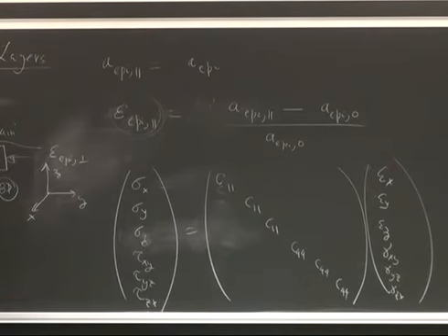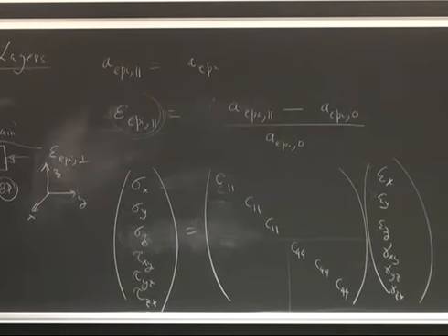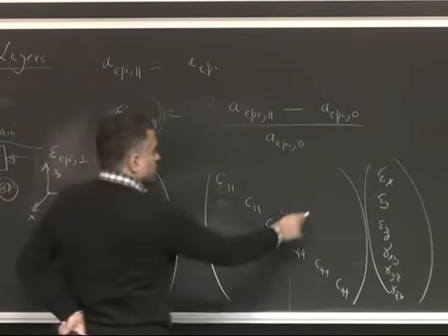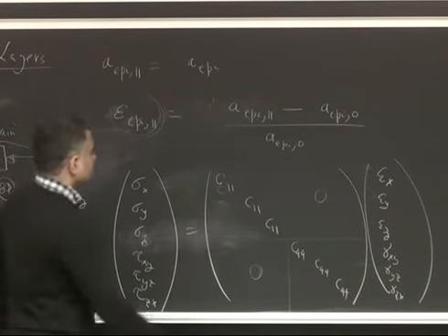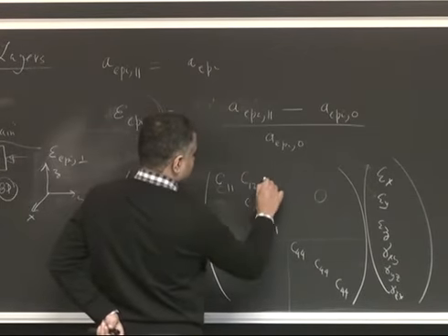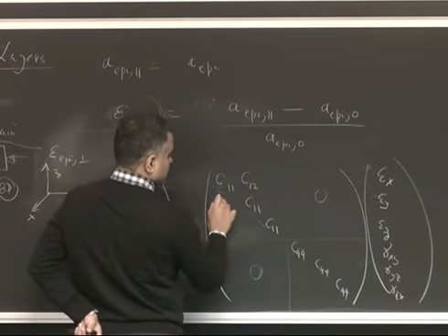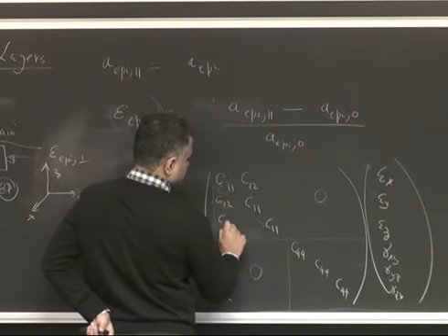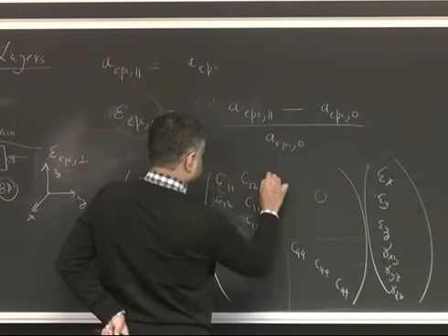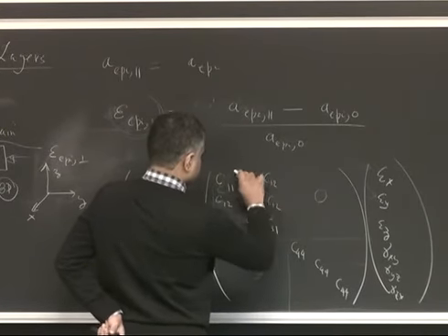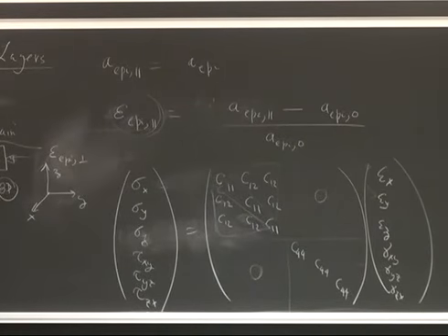And these are measured and tabulated for pretty much all semiconductors now. Then the off-diagonal elements are all 0 here and all 0 here. I'm not going into all the detailed reasons why. The off-diagonal elements in this block are all the same as well for a cubic crystal, so we just write them as C12. These are all the same, so you basically have three parameters.